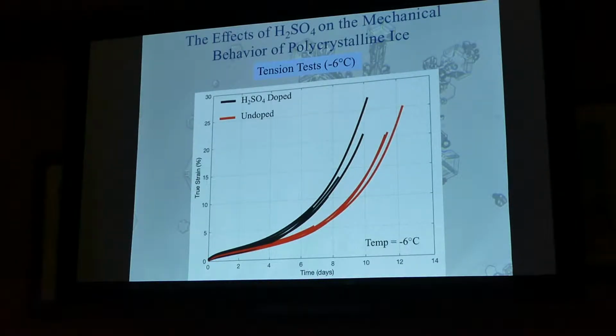If we look at the tension tested, so the creep tested specimens of ice, what you see is that the sulfuric acid here in black had, this is time down here and the strain up here, and we're letting it go for, in these tests, up to around 2 weeks. We saw that the sulfuric acid doped ice seemed to strain faster. So there's no cracking happening in these samples, all right? It's just stretching. And it stretched faster than the pure ice with just, I'm going to say this again, 10 parts per million of sulfuric acid added to the ice. So it's just trace amounts, just like it happens in nature. So this was a pretty interesting result, too, that we saw this in this different type of behavior.